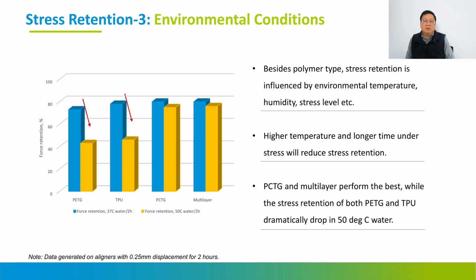So you can see, compared with a single layer like copolyester or TPU, after a few hours, like 2 hours at 50 degrees C, the performance drops more than 50%. So this is very key. Some brand owners advise the patient not to drink hot water or hot coffee while wearing aligners. But with ours, Maxflex, there is no problem.